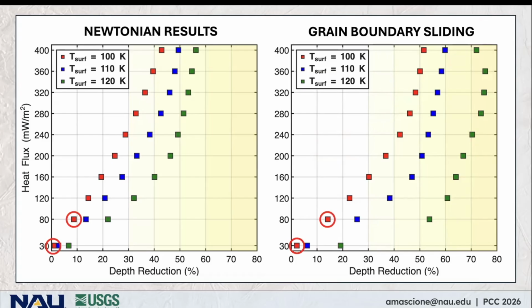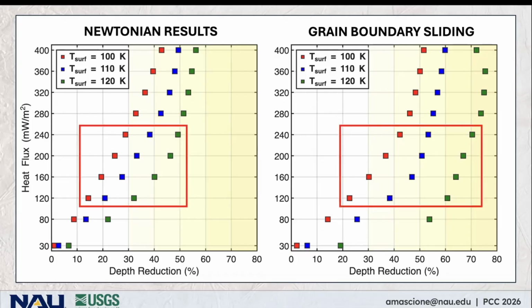Now at modern surface temperatures and heat fluxes, we see slightly more relaxation, up to 14% under the GBS rheology. But if we assume that sometime in Europa's past, it has experienced heat fluxes anywhere from 120 to 240 milliwatts per square meter, we begin seeing about 15% more relaxation on average compared to our Newtonian simulations.